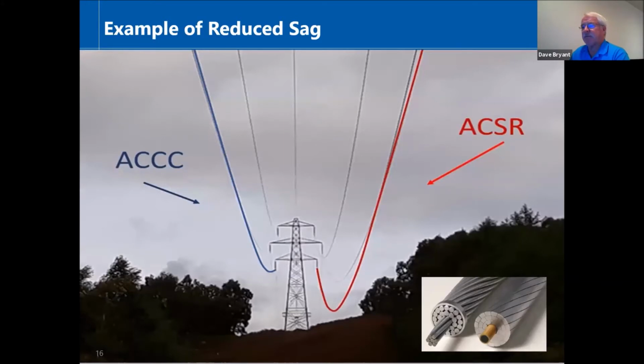This was a picture taken by SSEN in Scotland. They did a reconductor project, about a 45-kilometer reconductor project. They used 95% of the existing structures, and they replaced ACSR with ACCC. And you can see the pretty dramatic decrease in sag. They doubled line capacity, or actually got 2.5 times the capacity, and they mitigated the sag. So they were quite happy that they could use the existing structures. They were very happy that they could deliver more power to accommodate growing industrial demand in this particular region. And it was pretty much a home run. They actually won an award for their project in Scotland.